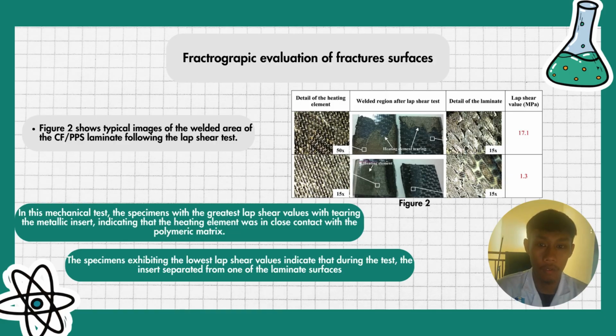Fractographic evaluation of fracture surfaces. Figure 2 shows a typical image of the weld area of the carbon fiber over polyphenylene sulfide laminate following the lap shear test. In this mechanical test, the specimen with the greatest lap shear values showed tearing of the metallic insert, indicating that the heating element was in close contact with the polymeric matrix. The specimen exhibiting the lowest lap shear value indicates that during the test, the insert separated from one of the laminate surfaces.